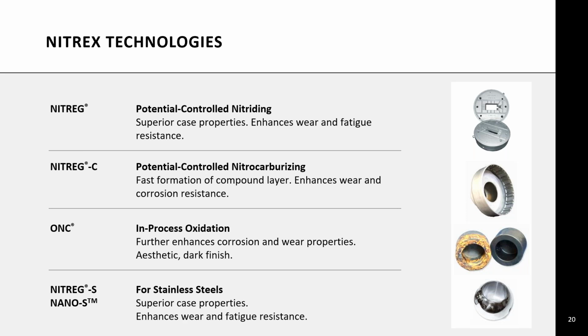Together with nitrocarburizing, you see in process post-oxidation or oxidation. The idea here is to basically transform the top of the white layer into magnetite and provide enhanced corrosion resistance. In parallel, we have developed Nitreg-S or Nano-S, two technologies specialized for stainless steel applications. Today, it is a very significant part of our market. Those two technologies apply to very many different materials, ranging from austenitic to martensitic materials, as well as duplex materials and precipitation hardened materials. Next, please.